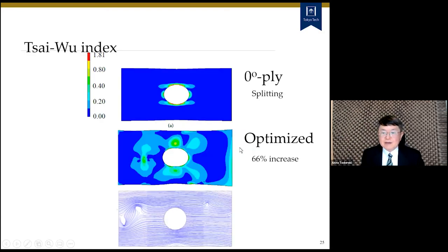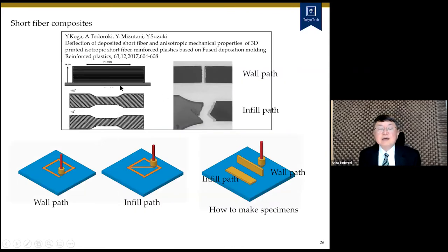So we optimized the results, but this is limited to the FEM analysis. We did not do the experiments. Just from the FEM analysis, we got a 66% increase of the tensile strength. And this shows the short fiber composite. The short fiber composite also has anisotropy, and it's quite difficult. Even for the tensile test specimens, it's quite difficult because if we use